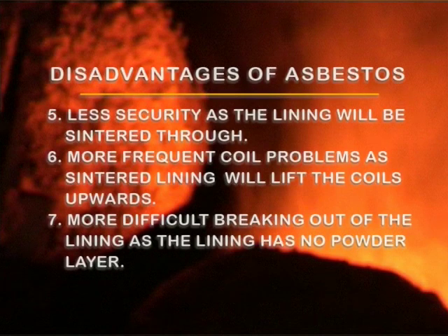Less security as the lining will be sintered through. More frequent coil problems as sintered lining will lift the coils upwards. More difficult breaking out of the lining as the lining has no powder layer.